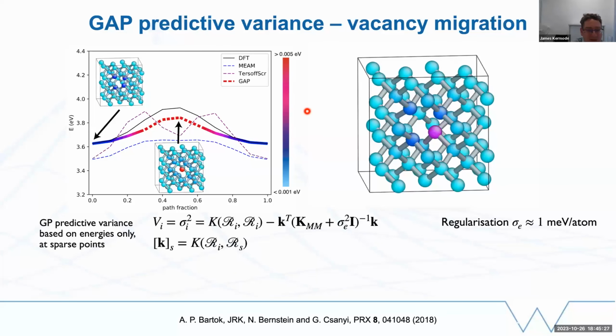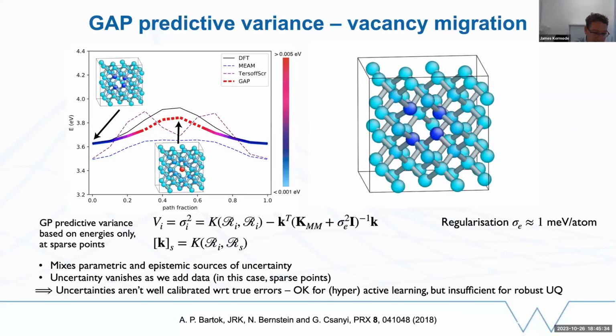But until recently, it wasn't really possible to make this very quantitative. So it was a sort of error indicator that's useful for things like active learning. But because it's mixing together different sources of uncertainty, it's mixing together contributions that are missing from the model with imprecise estimates of the parameters that we've got, it makes it hard to use as a real calibrated measure of uncertainty. And so it can't be used to put errors on properties like vacancy formation energies.